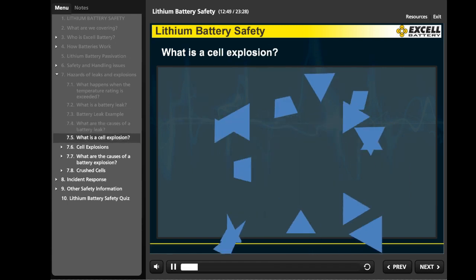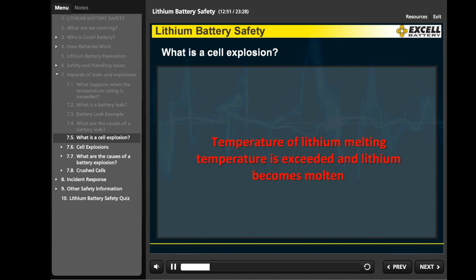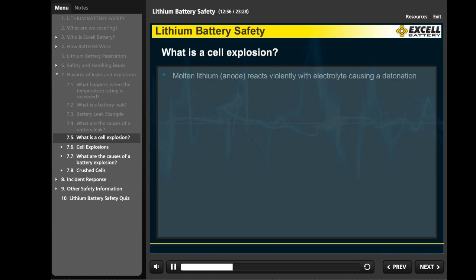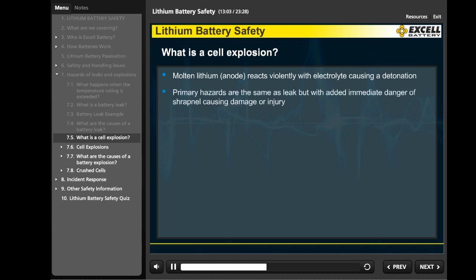What is a cell explosion? A cell explodes when the temperature of the lithium melting temperature is exceeded and the lithium becomes molten. At that point, the molten lithium will react violently with the electrolyte, causing a detonation. This is a tremendously high release of pressure, causing the battery and surrounding battery housing to break into many parts. Shrapnel from the battery parts flying through the air is an extreme danger that can cause damage, injury, or even death. Other than shrapnel, the hazards are a corrosive and toxic atmosphere, which are the same as a leaking battery.